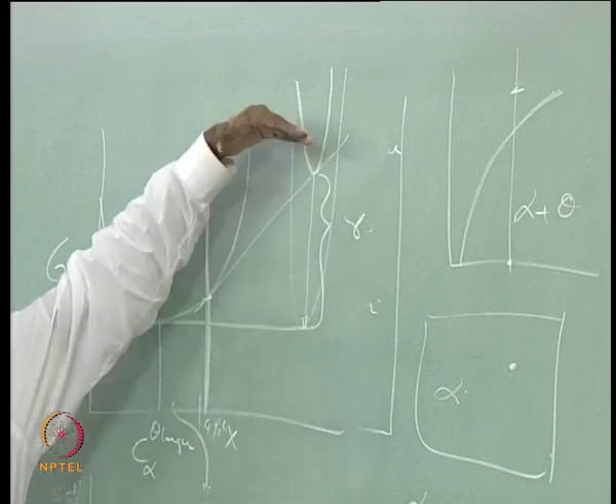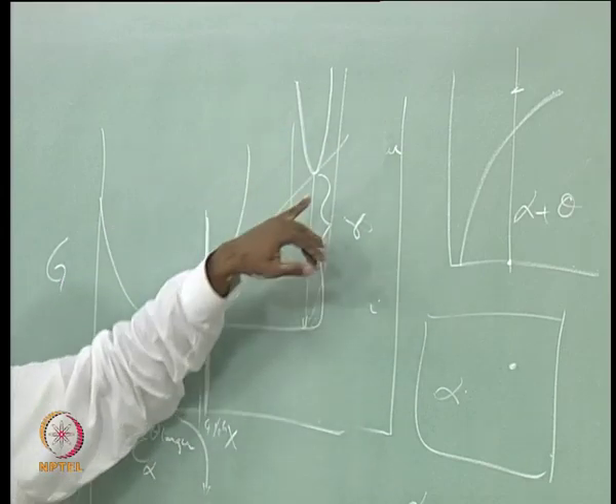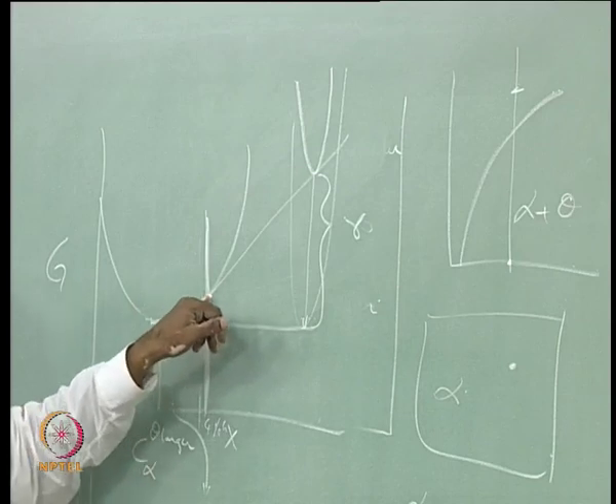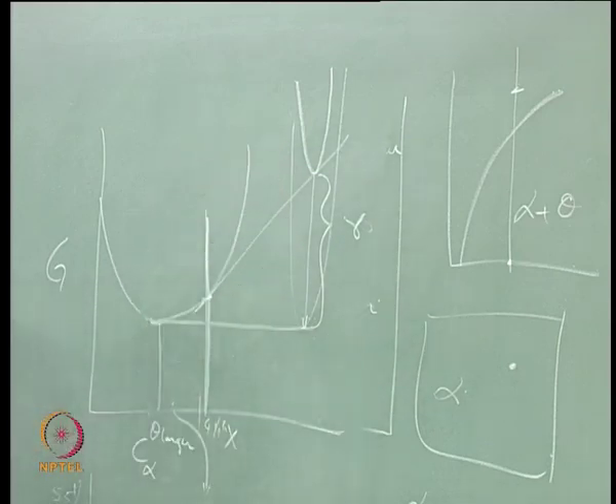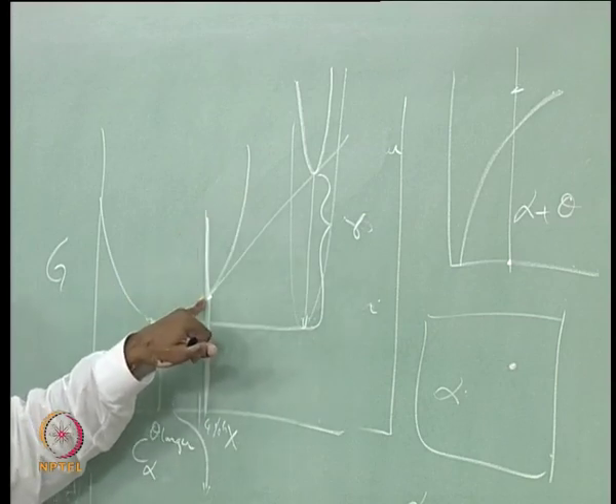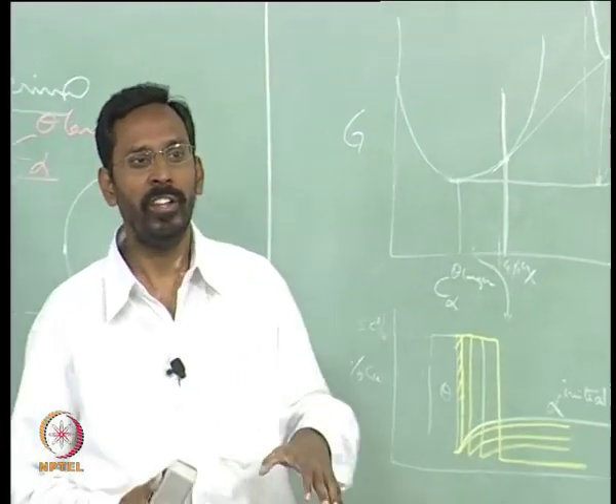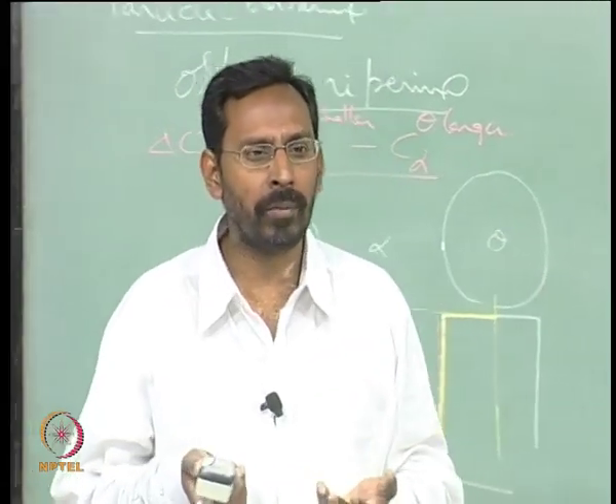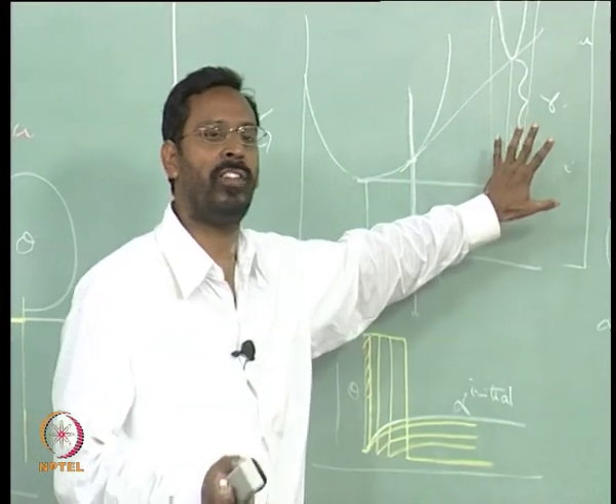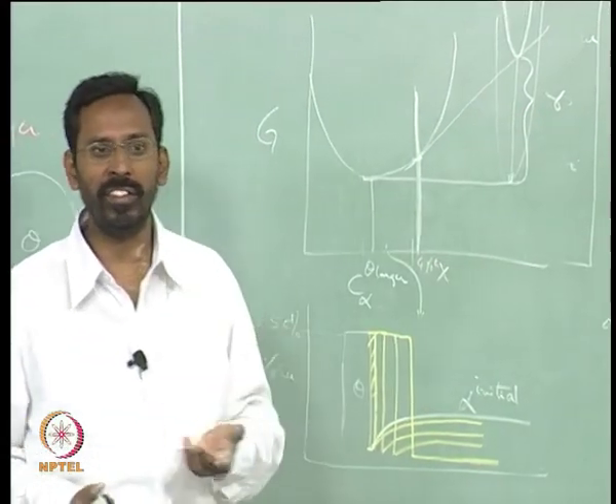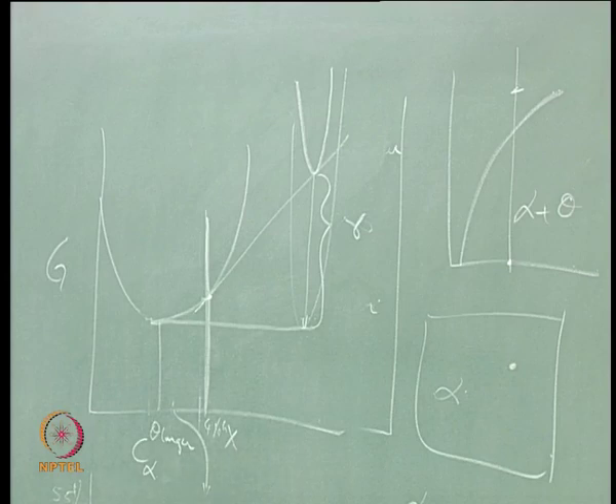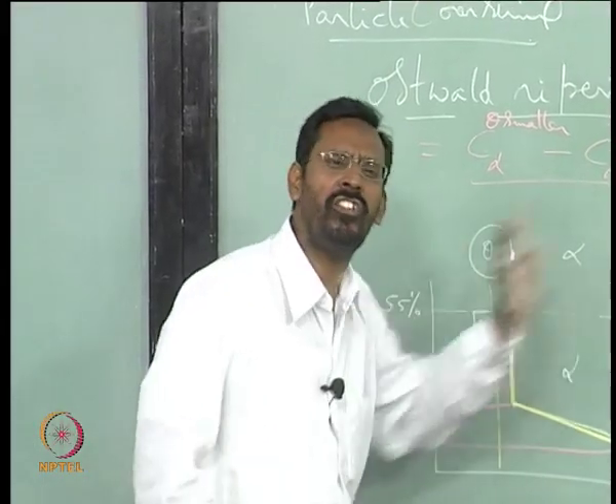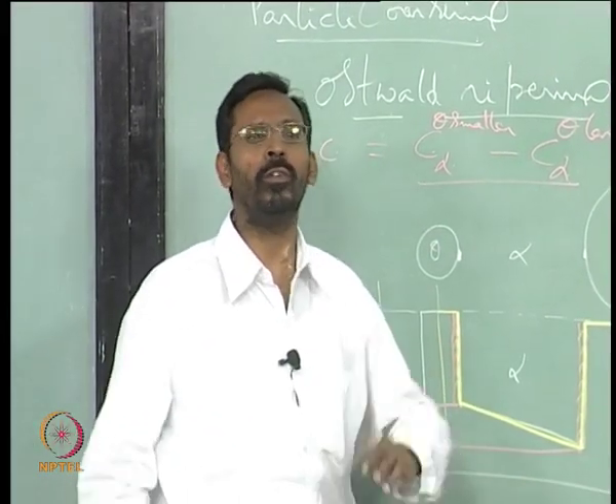So, the free energy gets lifted because of the surface energy, and at that particular moment you can say yes, it is in equilibrium, but the moment it grows even a little, it cannot be in equilibrium. That is the reason most free energy composition diagrams are drawn considering only the volume free energy. Capillarity effects or surface effects are not considered, and once you start considering them, these concepts come into the picture. In this case, we have considered the size factor, because there is a size distribution. If there was no size distribution, we would not have considered the size effect.